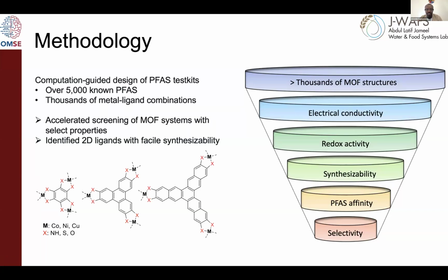Tim alluded a little bit to the porosity in his polymer, where they make these star-shaped monomers. For us, we get that for free in the frameworks, because with the ligand design, we can choose how porous the material is. So through size exclusion, we think that we can discriminate between the long and the short. But when it gets ultra short, by ultra short I mean right when it's down to like 4 carbons, that part has been challenging so far. We've been successful with 10 carbons to 6 carbons. Those we believe we can distinguish at low concentrations. When they get much shorter, it becomes challenging.